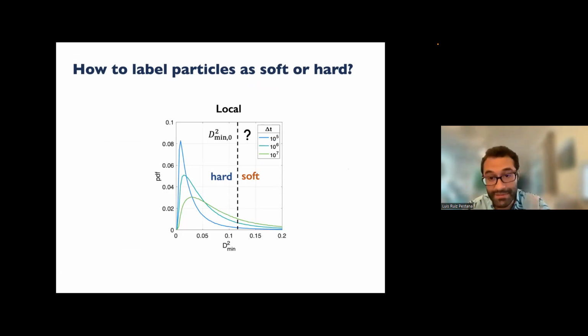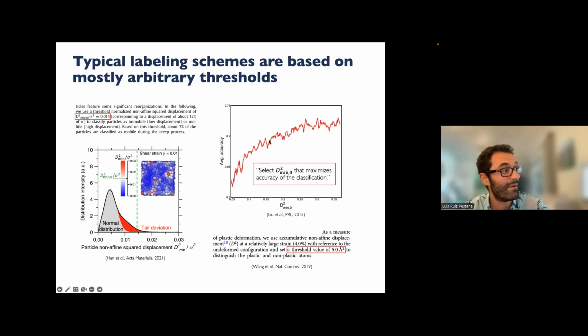And in fact, people working on this problem treated it exactly as an arbitrary threshold. Here I'm showing you three different papers, very high quality papers, where they are working on the same problem, trying to classify the particles in the glass as soft or hard. They have to set this arbitrary threshold on the D-min square displacement, which is the local non-affine displacement, and it changes in each study. And sometimes it's honestly kind of weird. For example, in the study on the left, the threshold is selected such that, in terms of real length units, it's about 12% of sigma. Sigma is the length scale of your particles.